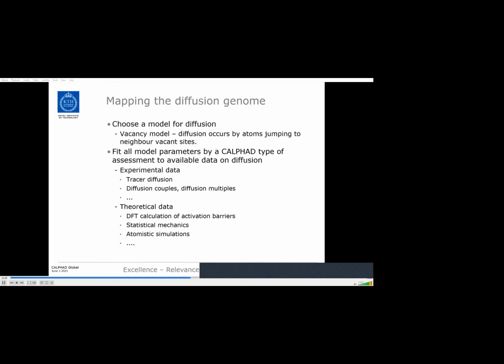So when we map the diffusion genome, we choose a model for diffusion, and usually we choose a vacancy model, which means that diffusion occurs by atoms jumping to a neighboring vacant site. And then we fit all parameters in the model by a CALPHAD type of assessment to available data on diffusion. And we have experimental data, which is tracer diffusion, diffusion couples, diffusion multiples, and so on. And there is theoretical data, DFT calculation of activation barriers. We have some input from statistical mechanics, atomistic simulations, and so on.